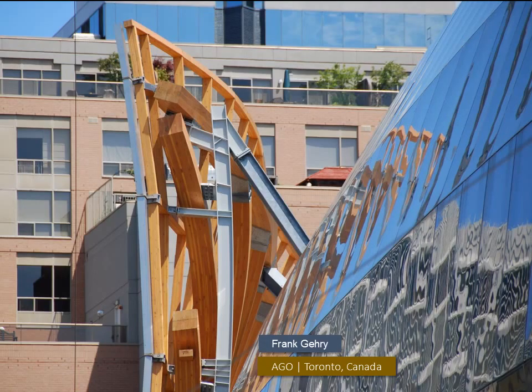The steel support system for the Art Gallery of Ontario used a combination of galvanized steel and zinc-painted steel. The long ribs were too large to fit in the galvanizing bath, and there was concern that the heat would distort them. The shorter components and the connections to the glulam timber were hot-dip galvanized, as they would fit in the bath, and distortion was not a concern.